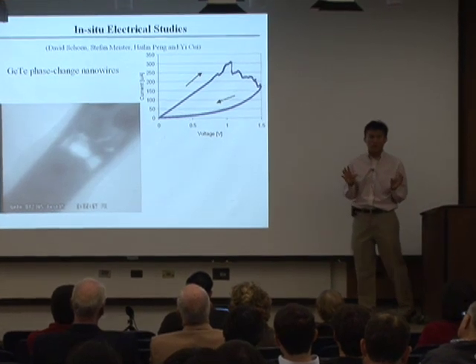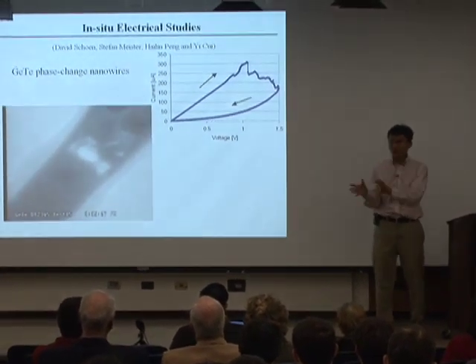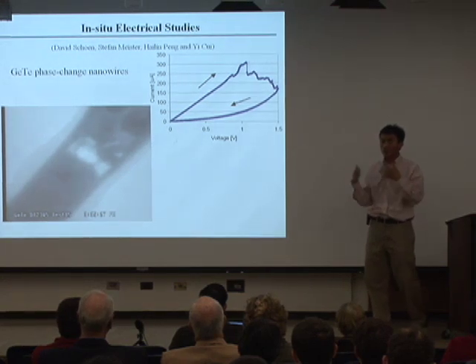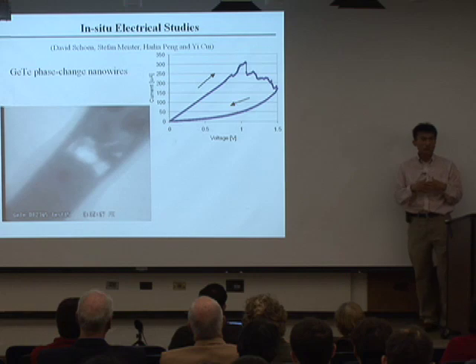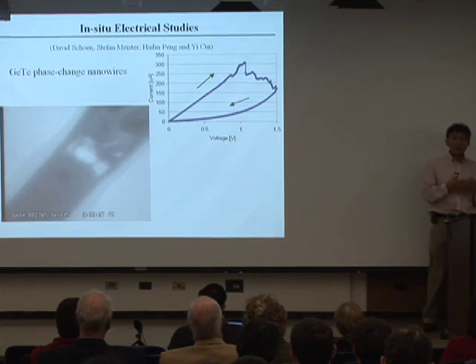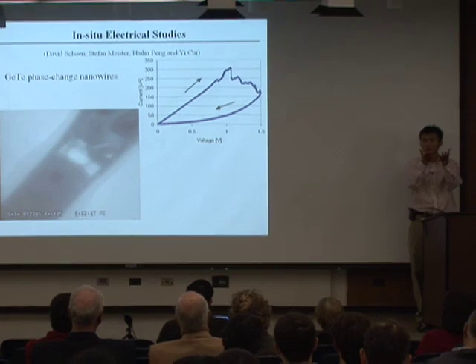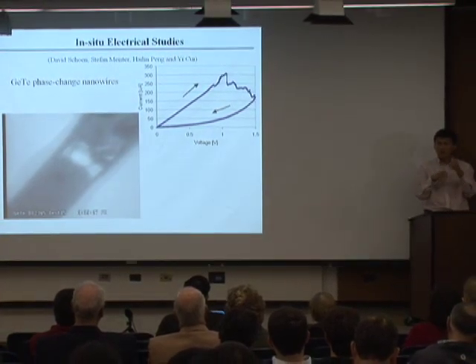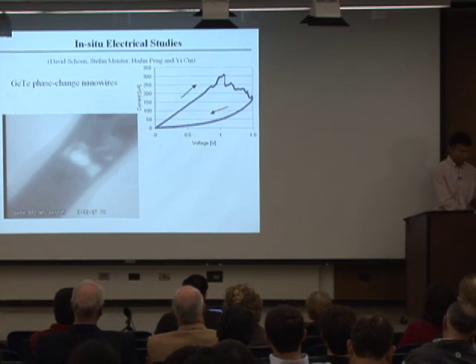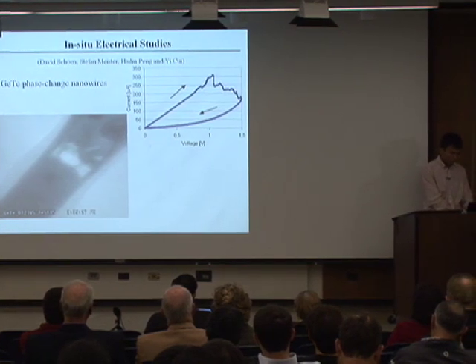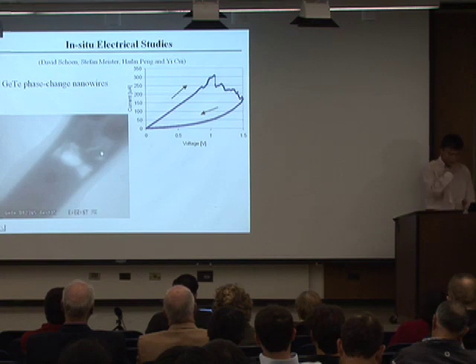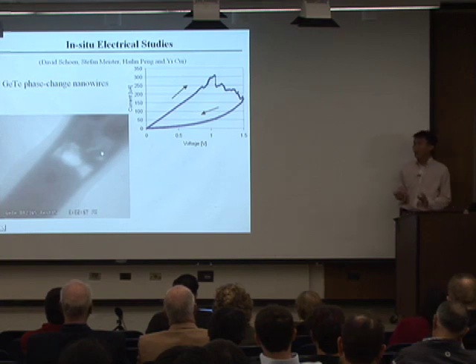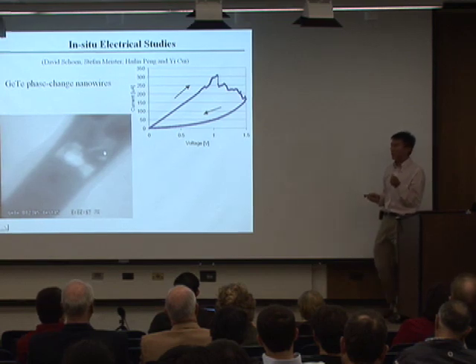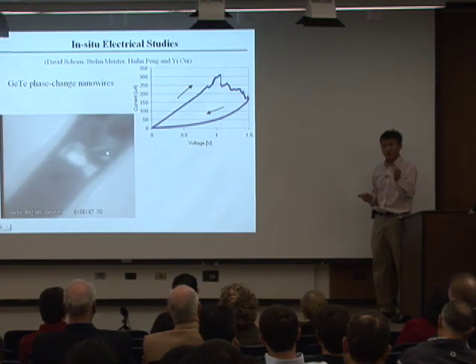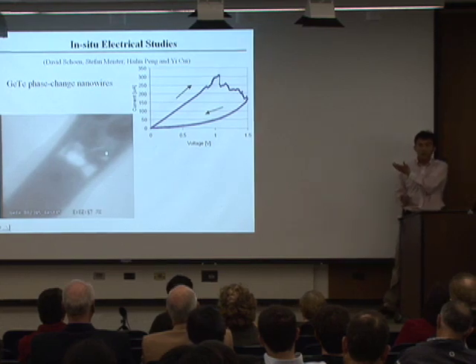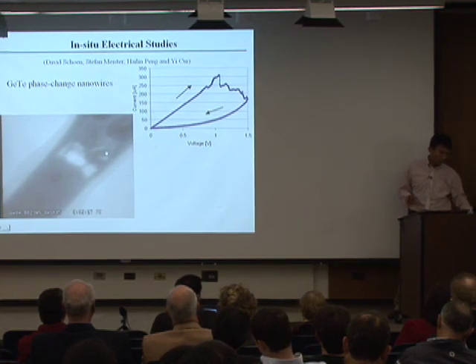In the phase change memory case, there's a crystalline to amorphous phase transformation as well. We would like to apply electrical current to do Joule heating to heat up the nanowire above its melting point and see what happens. So this allows you to do a memory, change it from crystalline to amorphous, amorphous to crystalline. Well, for a while, a lot of people think this is a simple memory mechanism, crystalline to amorphous, amorphous to crystalline. So now we can watch this in real time on the transmission electron microscope.